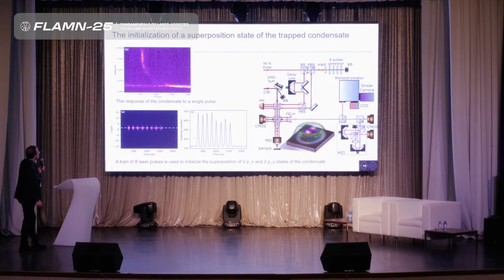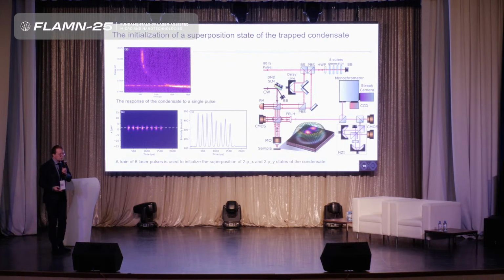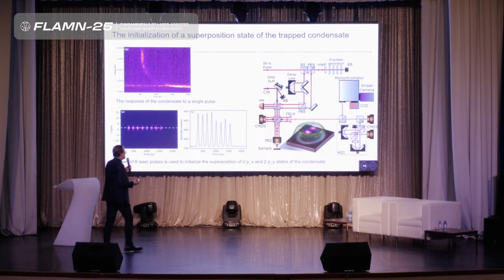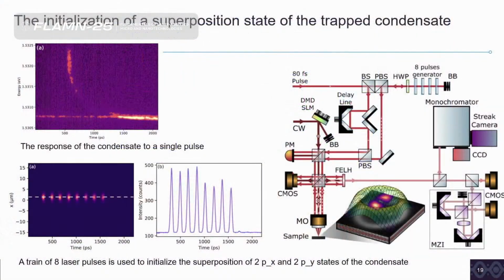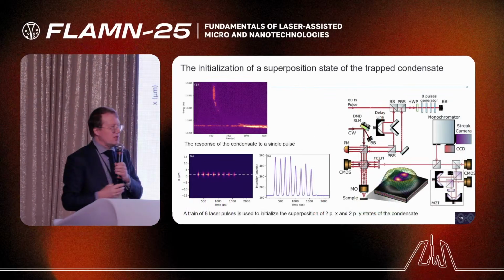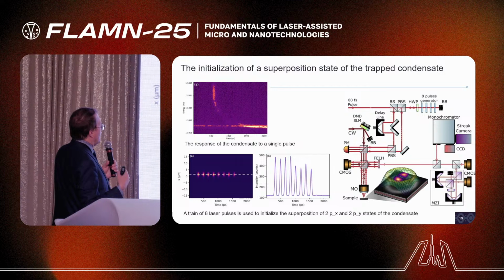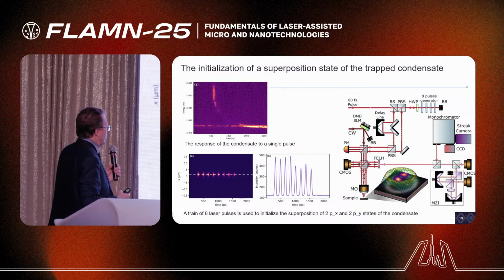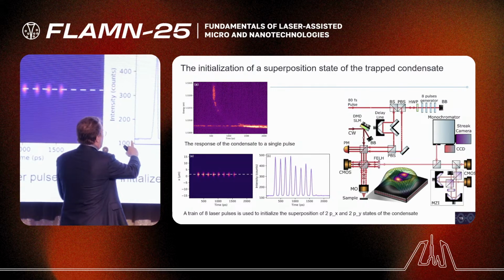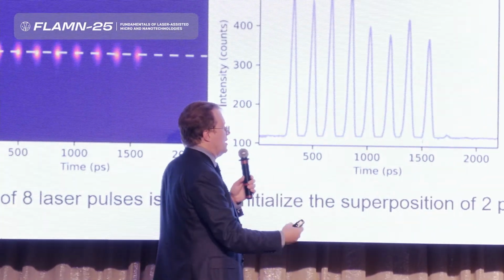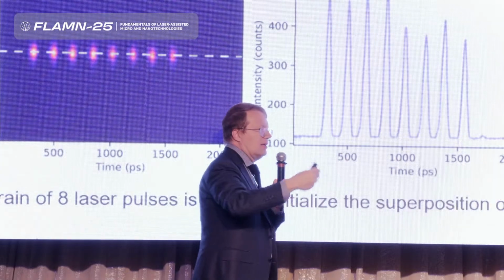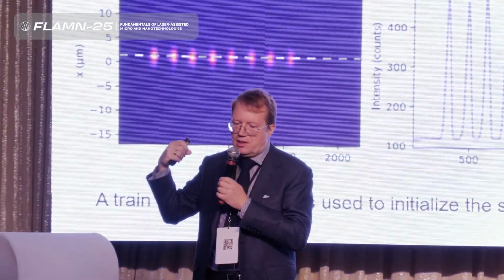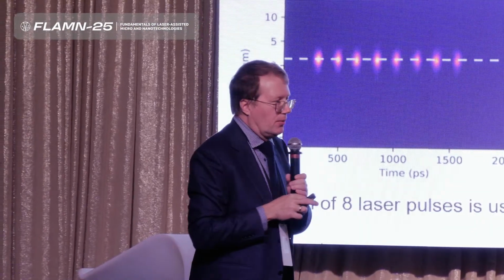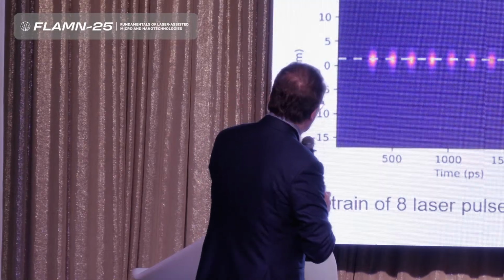And what do we do? First of all, we want to create a superposition of them. Initially, the system sits in one of these two states, for example, p x, so this state. So we need to kick it in order to create a superposition. And we do it with short laser pulses, femtosecond laser pulses. And actually, it turned out that in order to strengthen the effect of a pulse, you need to use a train of pulses. So here are 8 pulses that come one after another with carefully calculated spacing in order to provide a resonant effect.